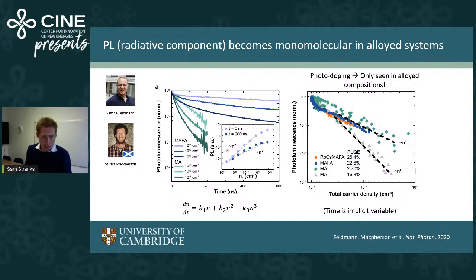And if we zoom in and look at that, what we see is that at time zero, so initially in this first region here, we can look at what type of kinetic it is, and we see that it's bimolecular initially in these formamidinium-rich samples. But then over time, after 200 nanoseconds, the kinetic actually changes and becomes quasi-first order, becomes monomolecular. And this is actually an example of photodoping, where one of the carriers in particular becomes very high in carrier density, and that starts to appear first order. So the recombination kinetic is somewhat first order. So this is the photodoping, and we see it particularly in the alloyed compositions.